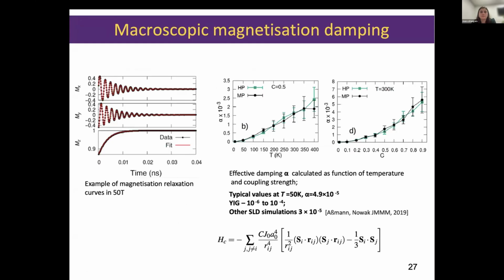We are also able to look at dynamic properties, such as calculating and estimating the damping within our framework. So we perform these magnetization relaxation experiments, and we can measure the damping as a function of temperature and of our spin lattice coupling term. The typical values of damping we obtain correspond with typical magnetic insulators such as YIG, and the damping serves as a way to parameterize our coupling term here, which allows for angular momentum transfer between spin and lattice.